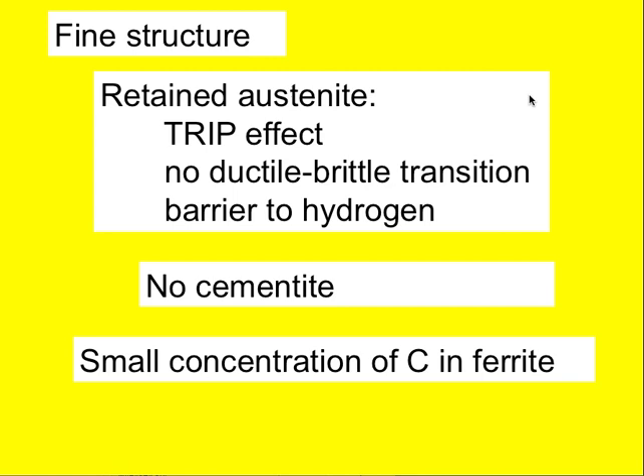You know that carbon in martensite causes embrittlement because of the tetragonal distortion of the lattice — it makes it stronger but embrittles. Here, even though the average carbon concentration is just 0.4 weight percent, we are actually pushing it into the austenite where it stabilizes the austenite, and it is doing good things. This is the cheapest way of producing austenite — to add carbon — whereas using things like nickel as in austenitic stainless steels is quite expensive.